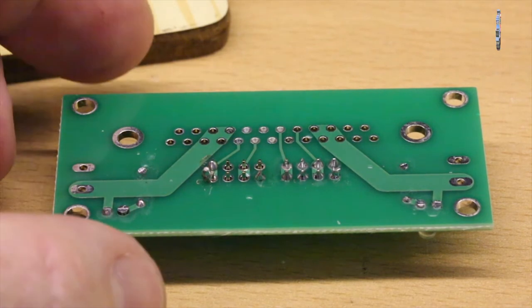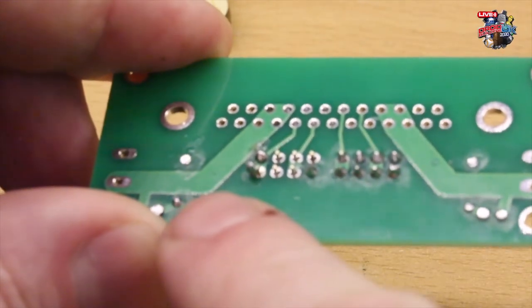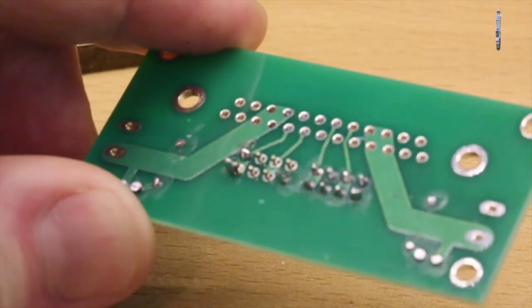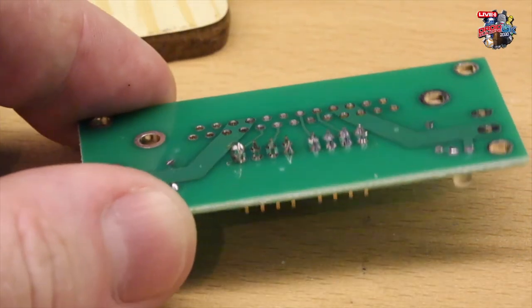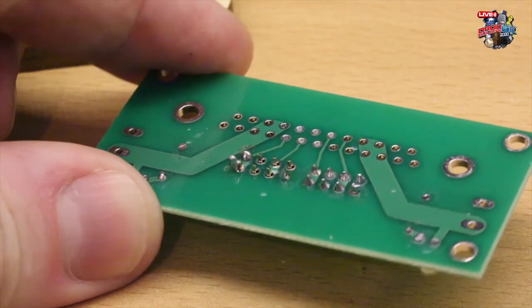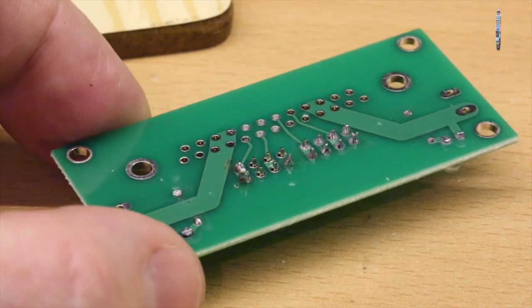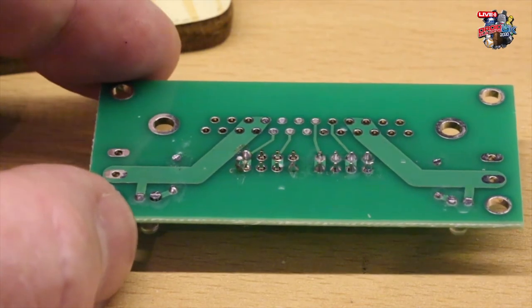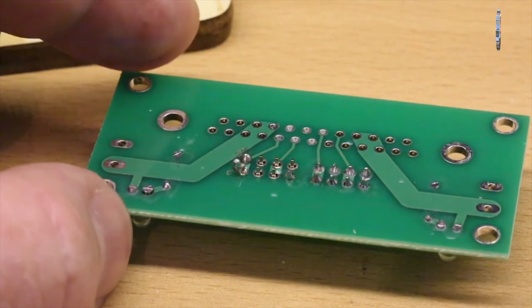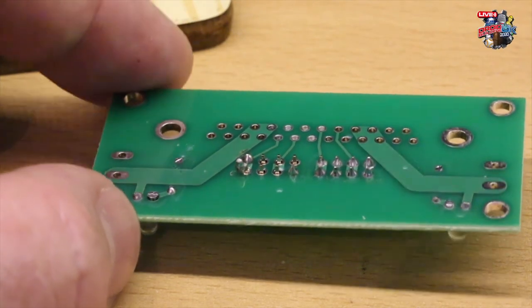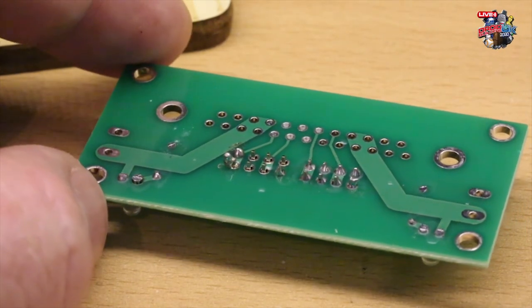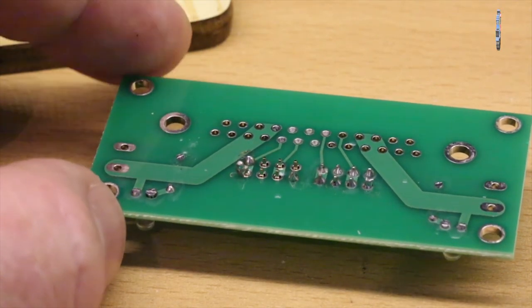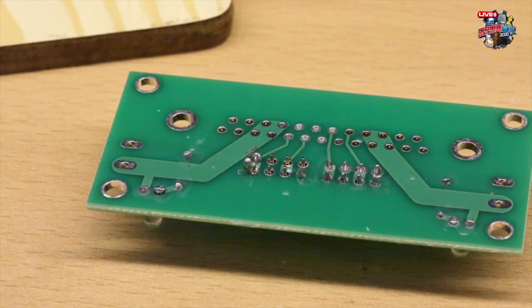Right, I've switched to a macro lens to show you a dry joint, but it's a bit tricky to show it. But if you can see this component down here in the corner, well this solder joint, it's not great. It's got way too much solder on it, and the solder doesn't actually go all the way around. That's typical. If you ever open anything that you've bought cheap, like a cheap radio off the market or something, you'll probably find that a lot of the components will look like this, and it might just about barely be working. With a dry joint, what happens is you get solder between the two components, and it might make kind of a mechanical joint for you, which means it'll stop the components falling out and moving around, but it won't make a good electrical joint. It's like if you were to push two bits of metal against each other, you would get an electric current would pass between them. But eventually you'd get like an oxide layer build up between those components, which would stop it working. And that's not a good thing, and that's what a dry joint is, where it worked to start with just by kind of mechanical contact, but it'll fail as an oxide layer builds up and stops the electrical contact working.